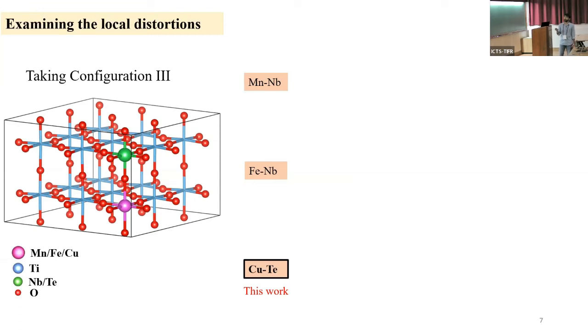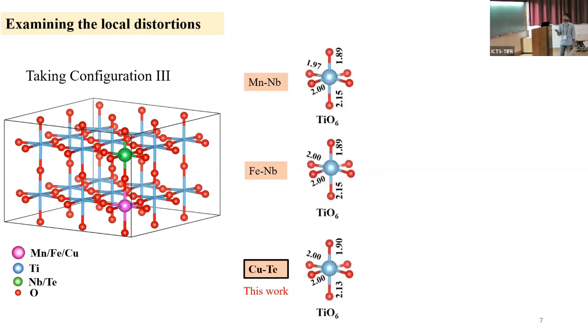Now, if one sees in such a configuration, one finds a local distortion. Let's consider TiO6 octahedra in all of these 3 configurations of MnNb, FeNb, and copper-tellurium, which is the present work. One sees that there is a finite off-centering present in TiO6 octahedra because of shifting of the titanium atom from its centrosymmetric position, as can be seen by the asymmetric bond lengths, above 1.89 angstrom and below 2.15 angstrom, which is pretty consistent in all of these 3